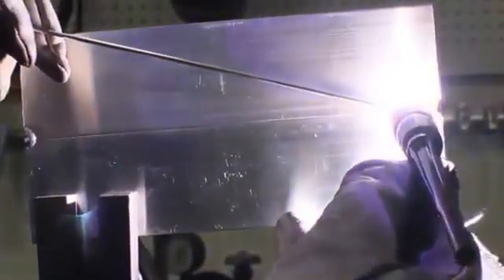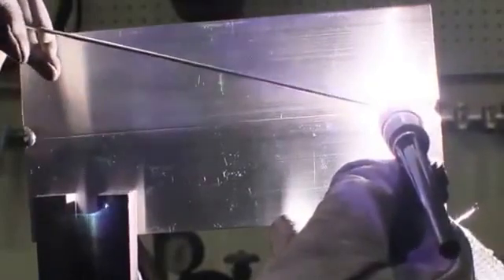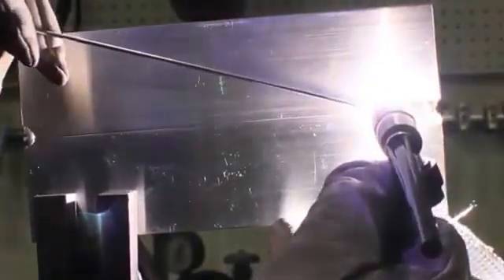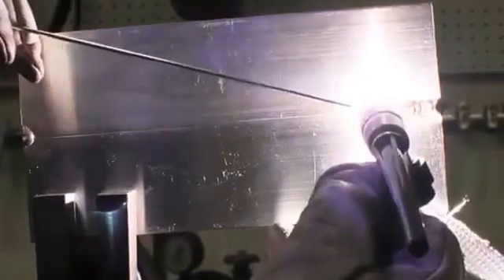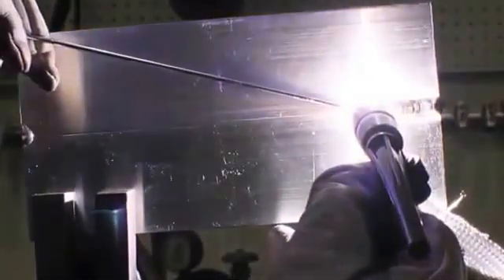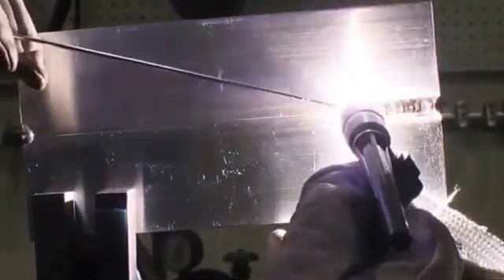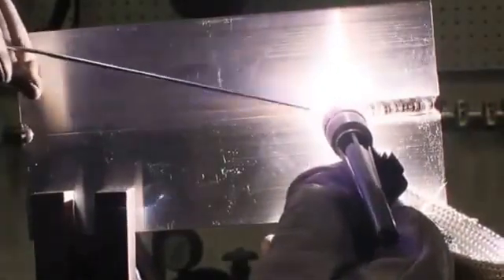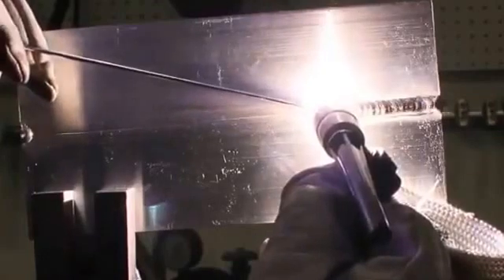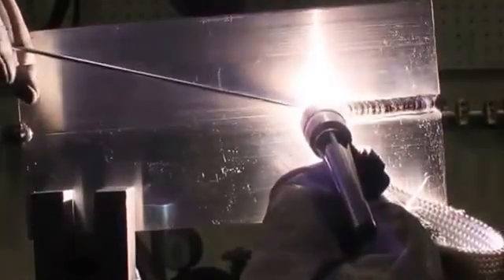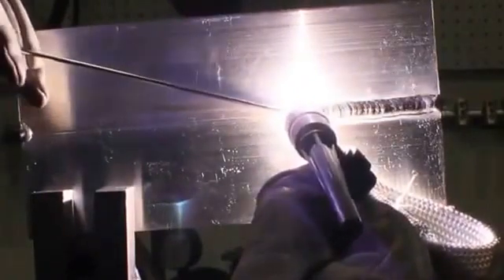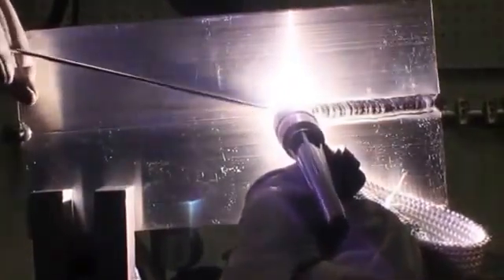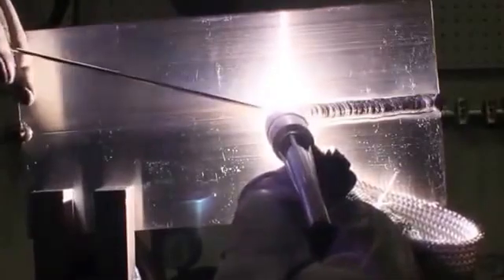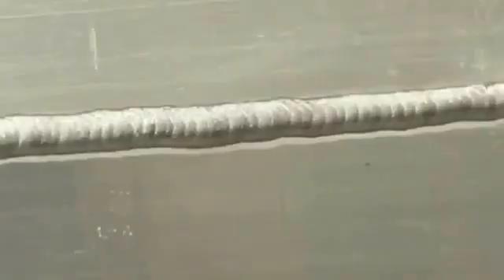And I'll explain a little bit as I go what's going wrong here. Occasionally you'll see a little spark here and there. Usually when you see a spark on aluminum and some other metals, that means you're getting a little bit of porosity here and there. That means something's trying to outgas, and as it's solidifying, it's not quite able to outgas, and it kind of explodes a little bit. And you can see as I'm going here, it's not a horrible looking weld, but something doesn't look quite right. So when I get finished with this, I'll explain to you what that is.